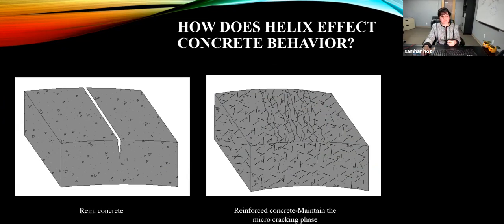Conventional section does not behave as a true composite system since concrete must first crack before reinforcement becomes active. On the other hand, Helix perform as a composite system with the concrete, adding a quantity of Helix distributed throughout the concrete section provides multi-directional reinforcement network and create a ductile system. This significantly changes the failure mechanism of concrete from sudden, brittle failure resulting in complete damage to the concrete into ductile system that's more resistant to cracking and localized damage.